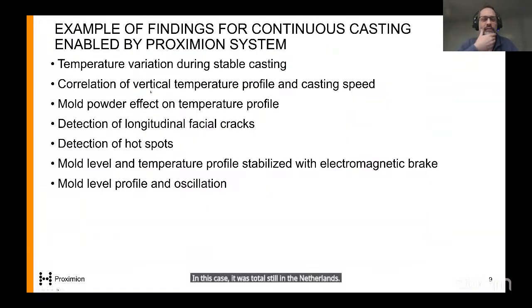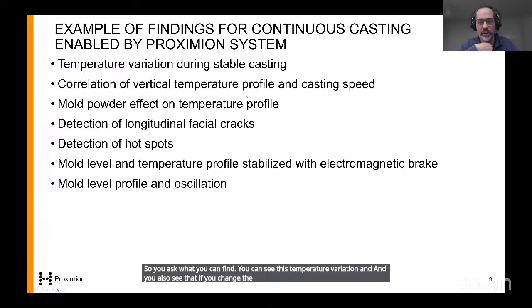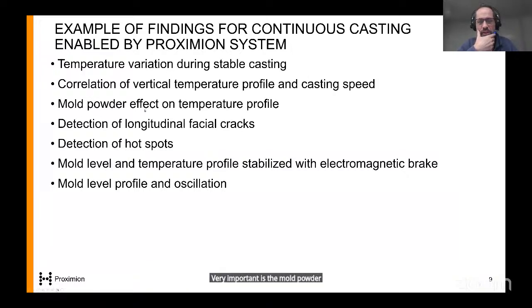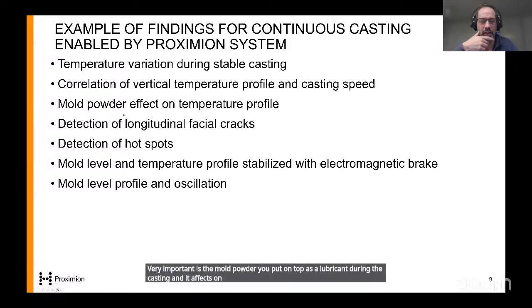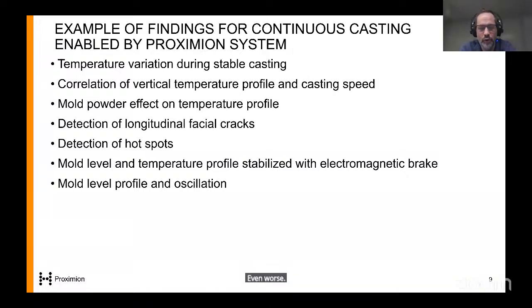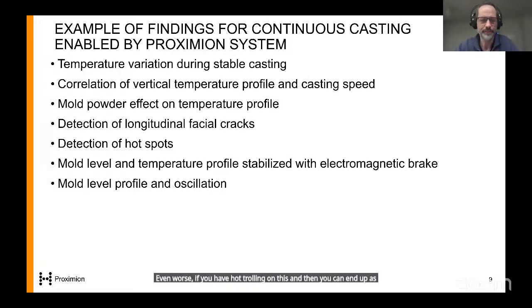You can see this temperature variation, and you also see that if you change the casting speed, you can see how that affects the solidification by monitoring temperature. Very important is the mold powder you put in on top as a lubricant during the casting, and its effect on the temperature. A common problem is cracks on the surface, which are quite expensive to remove. And even worse, if you have hot rolling on this, you can end up with defects in the final product.